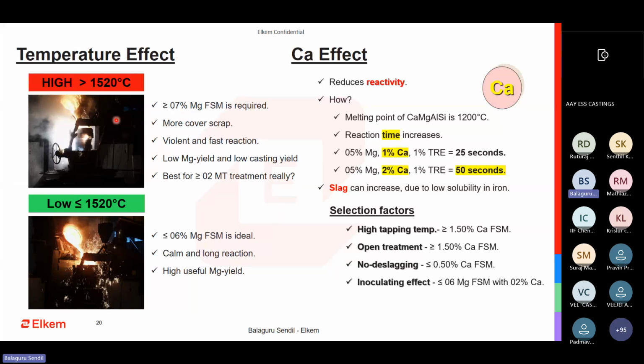So my focus here is: how would I get the tapping temperature lower? If I have high tapping temperature, I need to have more cover scrap. The reaction is violent and fast, low yield. Maybe it is suited for bigger treatments. Not ideally. We have foundries in India who do 30-40 metric tons of casting, who take 5-6 tons of treatment, and they still use a 5% magnesium. So it breaks the myth.